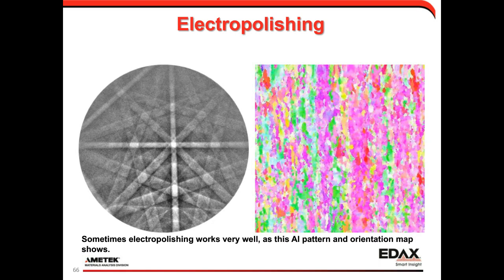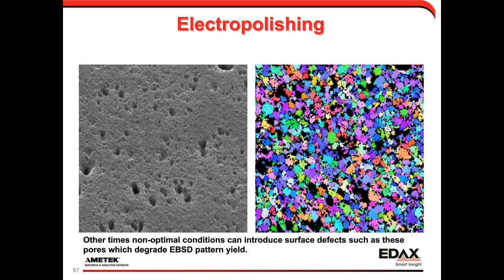And so with electropolishing, it can work very well. This is an example from an aluminum foil. So we get a nice pattern, nice maps. And sometimes not so well. So this is, again, an aluminum alloy, but here we see some porosity on the surface. We see our indexing rates on the right are not as high as we saw in the previous example.